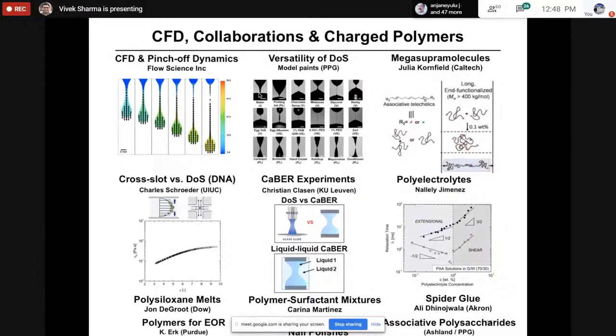As you increase the viscosity, the neck thinning becomes slower and slower. If I increase the viscosity to maybe 100 times water viscosity, the neck shape changes, as you can visualize in dripping onto a substrate. The neck radius now decreases linearly with time instead of t to the power 2/3. Actual viscosity plays a role for viscocapillary thinning, and plays no role for inertia capillary thinning. For water and ethanol there will be some difference because the surface tensions are different, and that changes the driving force for thinning. But viscosity will not be the reason for the difference between pinch-off dynamics of water and ethanol.